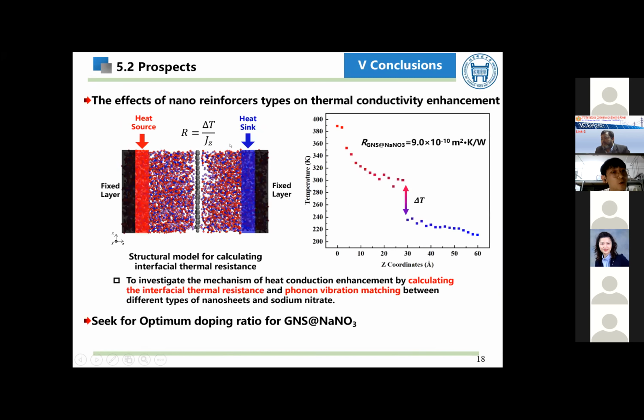As for the prospects, firstly, we intend to investigate the effects of nano-reinforcer types on thermal conductivity enhancement by comparing the interfacial thermal resistance of different kinds of nanoparticles with sodium nitrate. The calculation model of interfacial thermal resistance is shown in the figure, a sandwich structure, and the interfacial thermal resistance can be obtained by applying a heat source and heat sink at both ends.